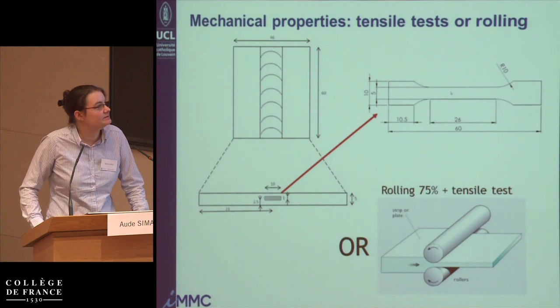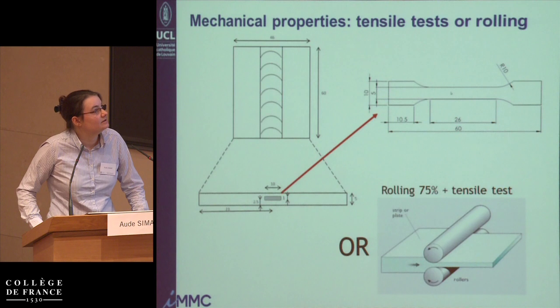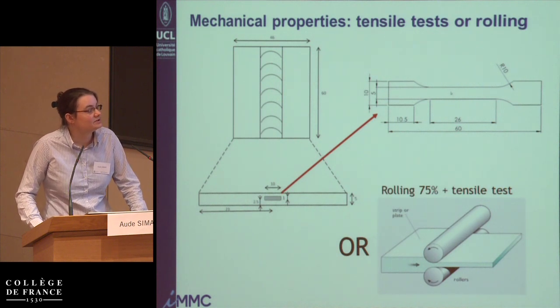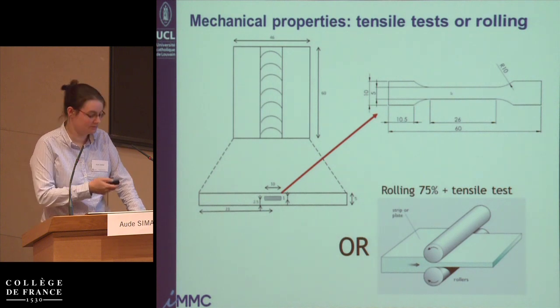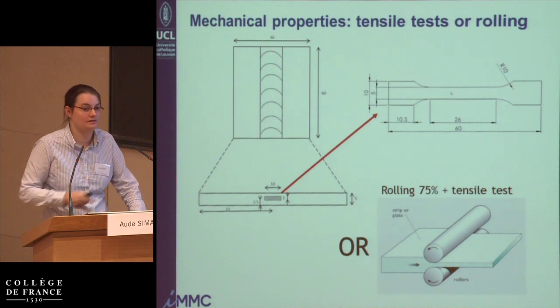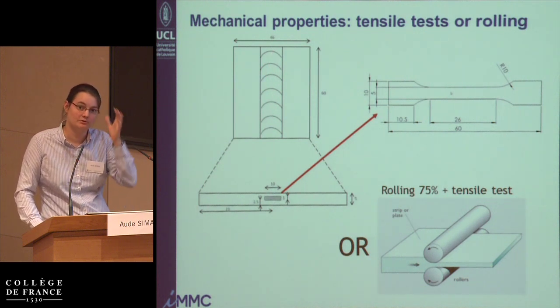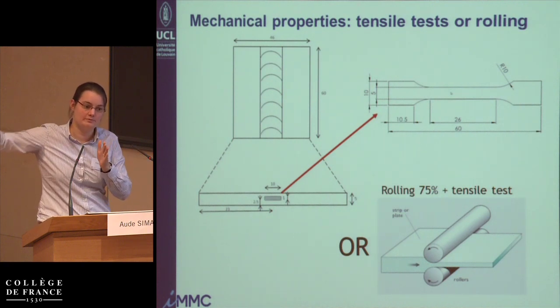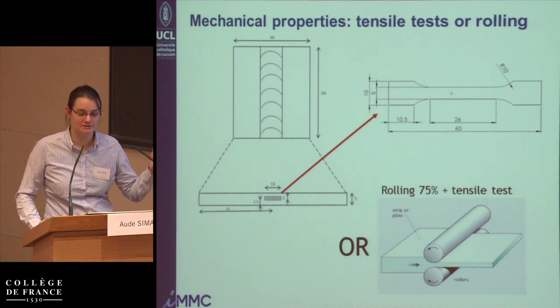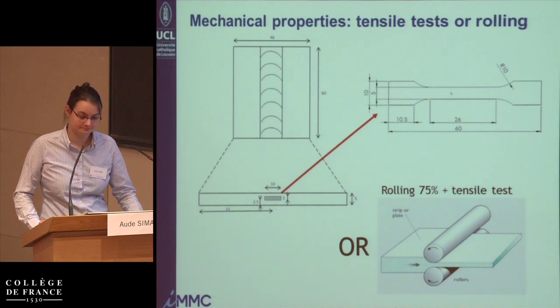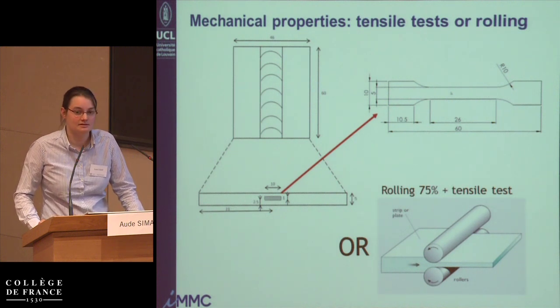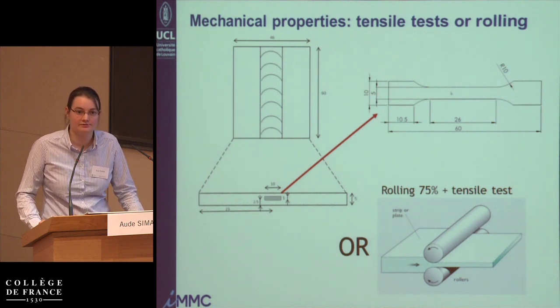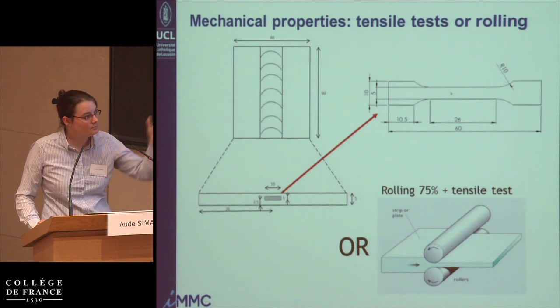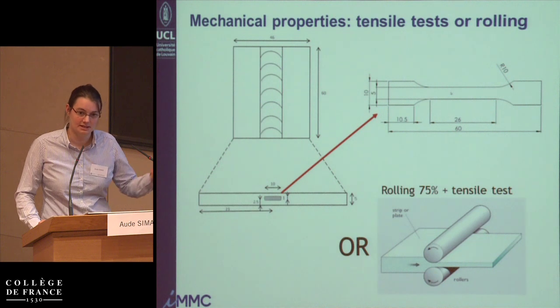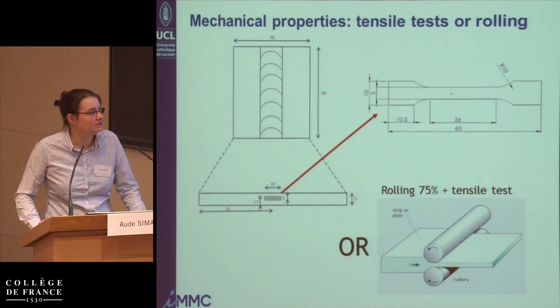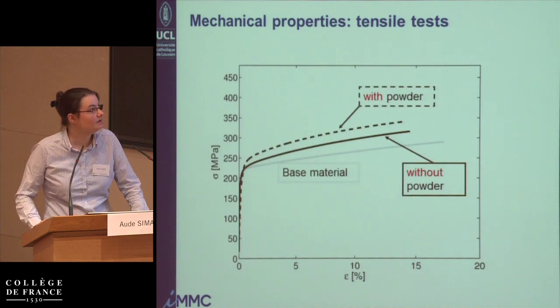So, looking at the mechanical properties of these materials, we did some tensile tests on these materials. Now I've told you that here is our weld. I've told you that we only do passes on one region of the weld, and we're not making a full macroscopic material for these tests, and so we have very small tensile samples, and this of course makes it harder to have reproducible results, but still we can work with that. And we also did some rolling of these materials, and I'll detail a little more later why we actually roll these materials.